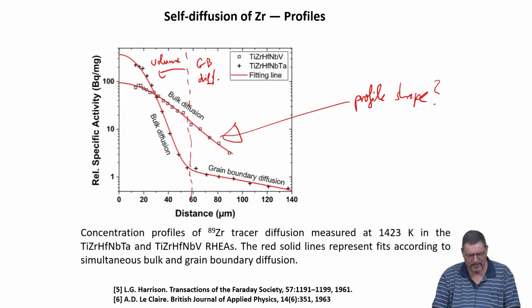Could you think of a reason why it's so different between the tantalum-containing and the vanadium-containing material? You said that a smaller size of precipitate means it is mostly preferred at grain boundaries, so that's why. Yeah, I think it is related maybe also to the homologous temperature again and the relative importance of volume and grain boundary contributions. They are always both there, right? But both are near par, both tantalum and vanadium. I think both are nearly equal. Yeah, the two alloys have a slightly different melting temperature. Yes. So you cannot always judge from the melting temperatures of the constituents. You always have to look at the alloys themselves, right?